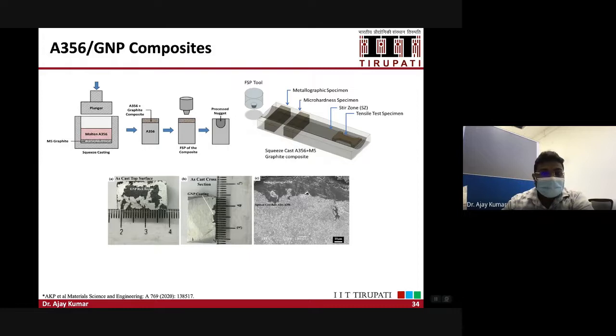The third example I would like to show you is the aluminum graphene composites. You know that graphene is a very famous material and it has high strength, and a lot of other applications. So we studied aluminum GNP graphene nanoplatelet composites. And here we applied a hybrid approach of making these composite materials. We coated the GNP on the aluminum A356 alloy using the squeeze casting method, and then did FSP to distribute the GNP in the composites.